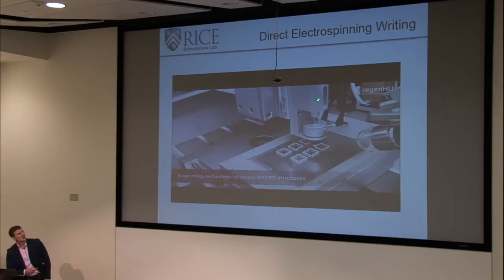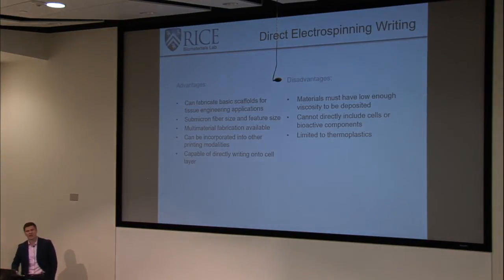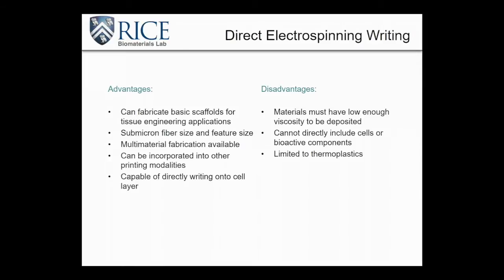this is a commercially available 3D printer that traditionally uses extrusion printing methodologies. So in this case, they've 3D printed a gelatin substrate here, and then through electrospinning on the same printer, you can create a directed woven mesh in the center here. So we have not only the mechanical properties on a macro scale of this larger construct, but you can directly electrospin your fibers from polycaprolactone or gelatin or whatever you're using as your polymer melt into this scaffold. So you can combine this printing methodology with other methodologies. And that's something that we'll be investigating more in the Biomaterials lab if that kind of nanoarchitecture is at all of interest to you. And like I said, the advantages here are we have much more relevant microarchitectures than we can possibly achieve with traditional extrusion methodologies.